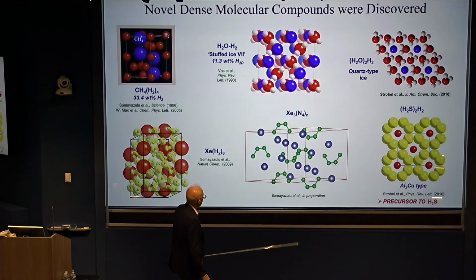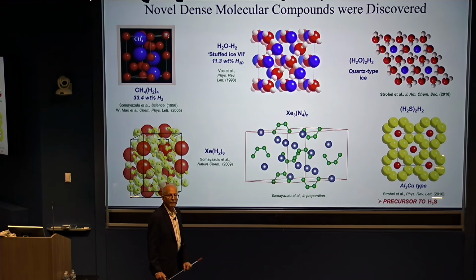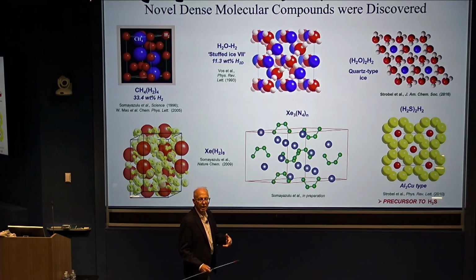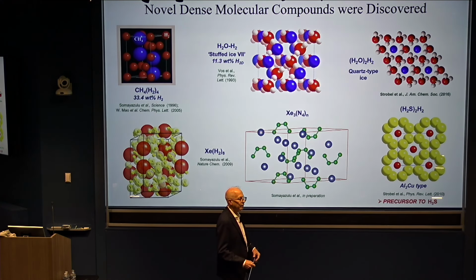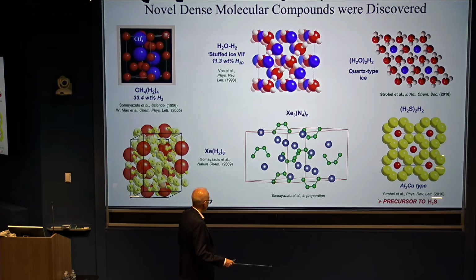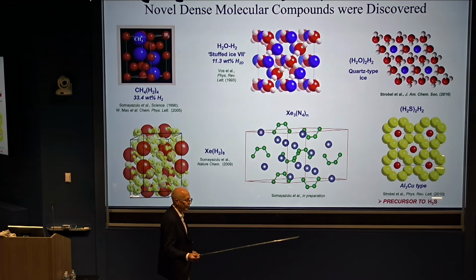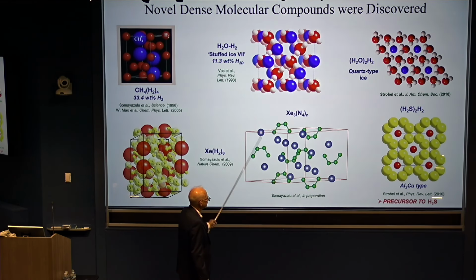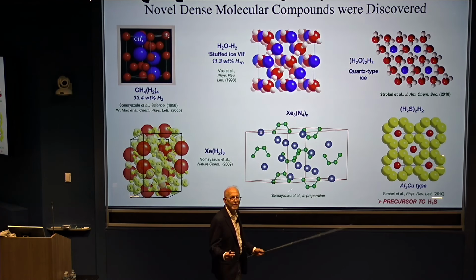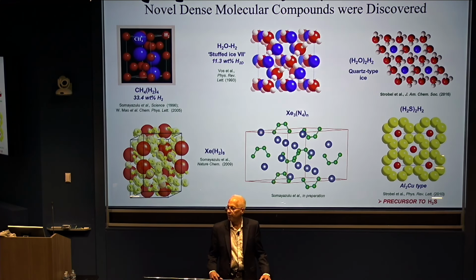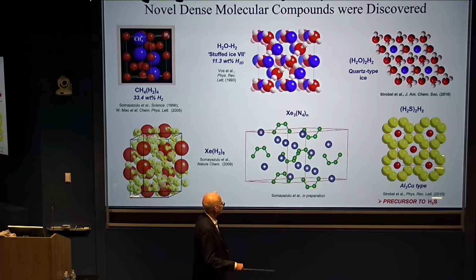So part of this effort that we were involved with involved just mixing different elements or molecules and doing various kinds of studies to look at what kinds of compounds would form at a range of pressure. In fact, during the 90s and later, we found that if we mixed hydrogen with various elements, kind of along the lines of what was proposed, you could make new materials. And we found a lot of really intriguing structures.